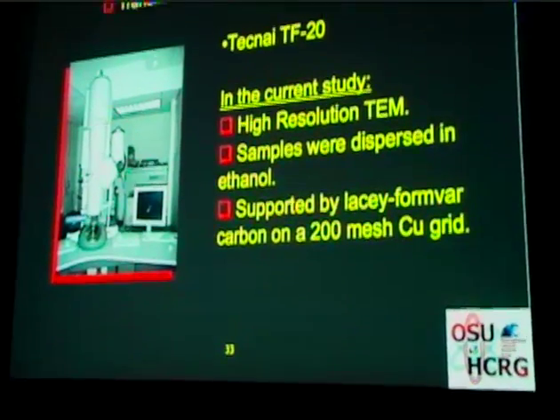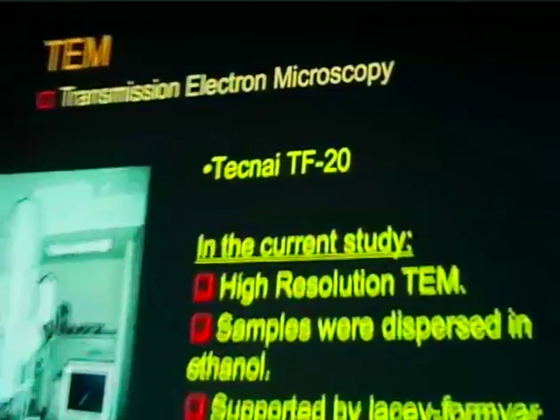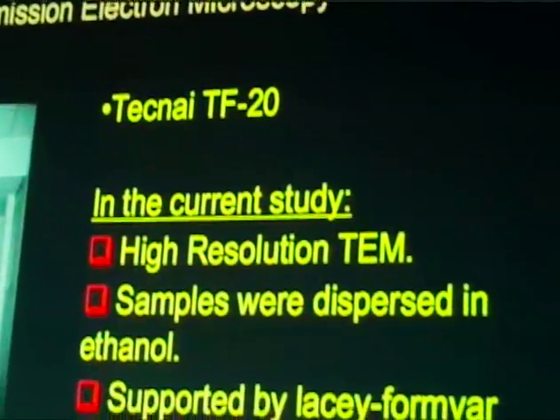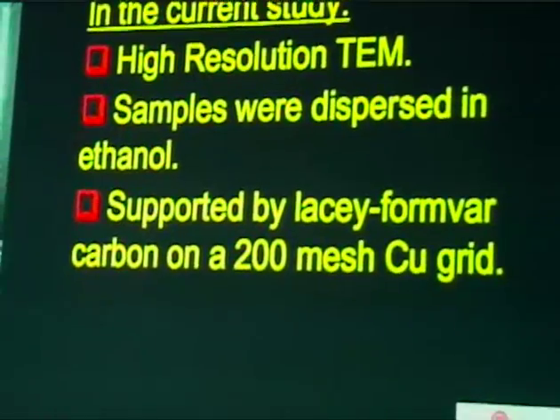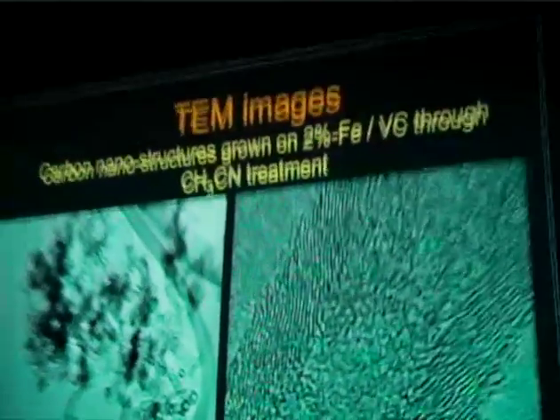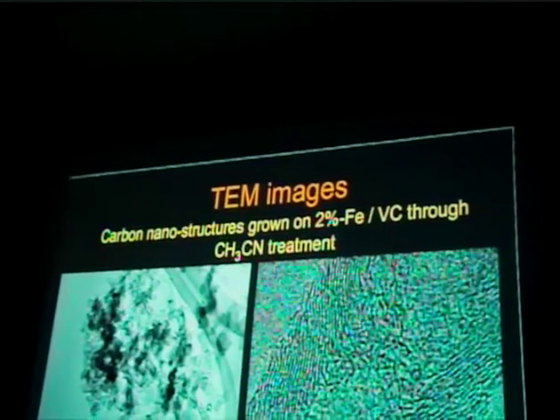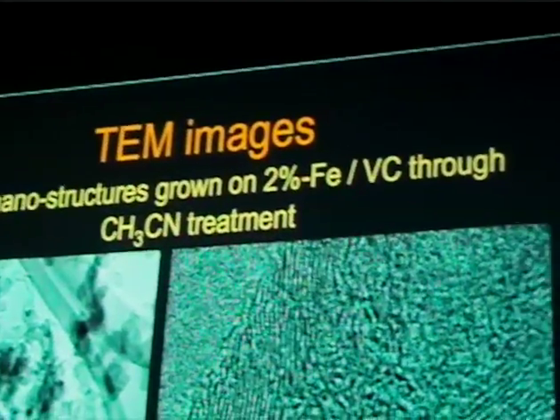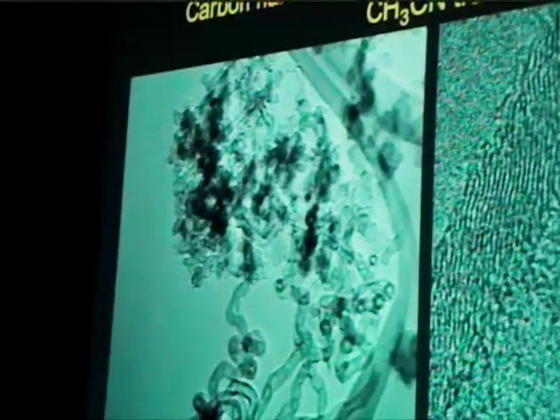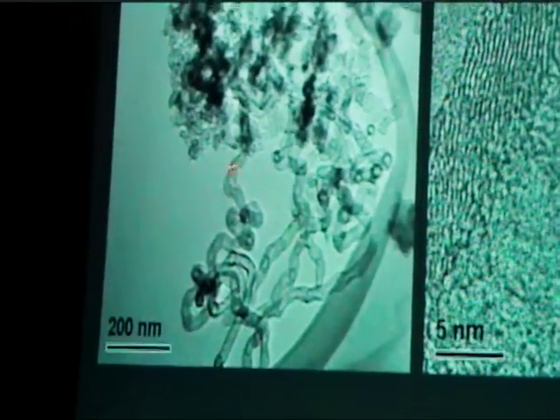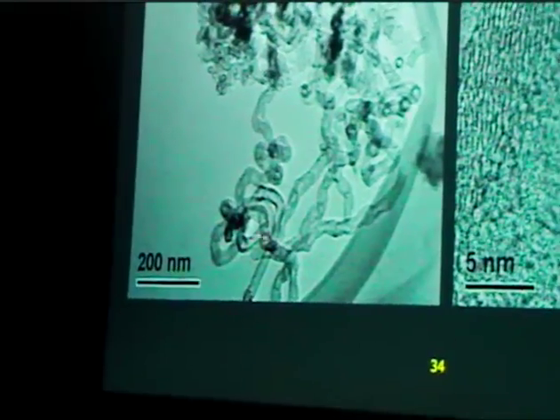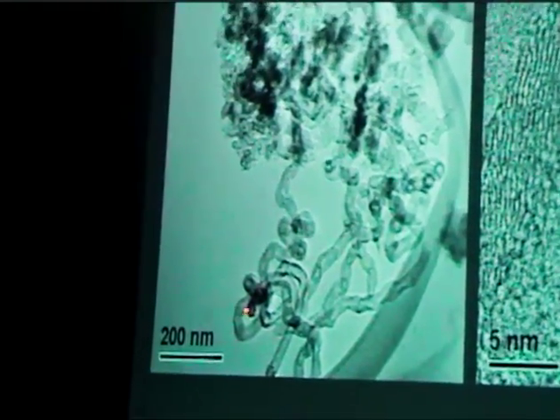So what do these materials look like using transmission electron microscopy? In this case, we were using a Tecnai system. Here are carbon nanostructures grown on iron-containing Vulcan carbon support after acetonitrile treatment. You can clearly see the carbon fiber growth, and at the tip of these, you can see the metal particles. In this case, these are the iron particles.